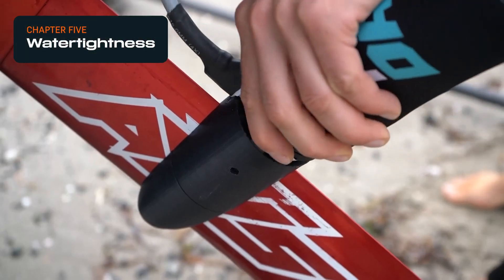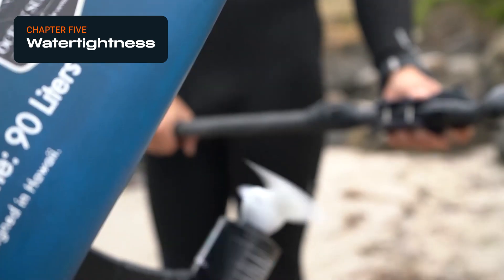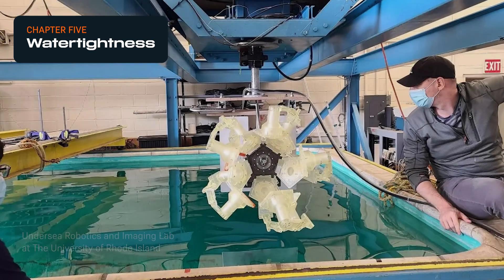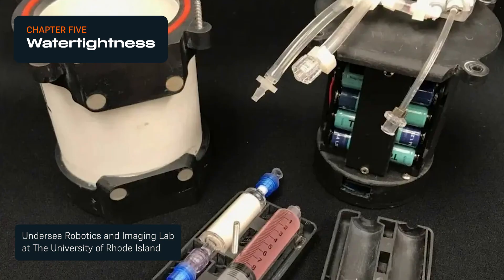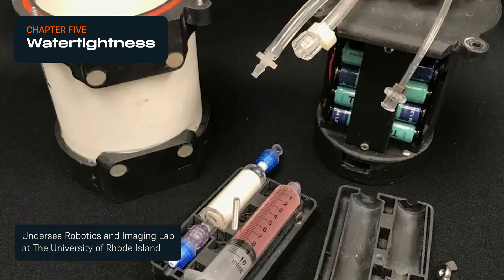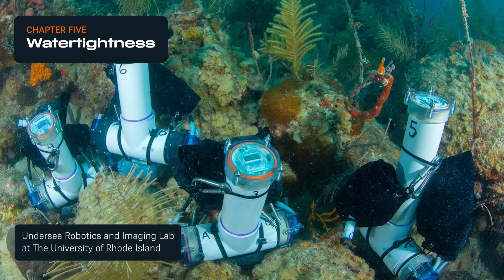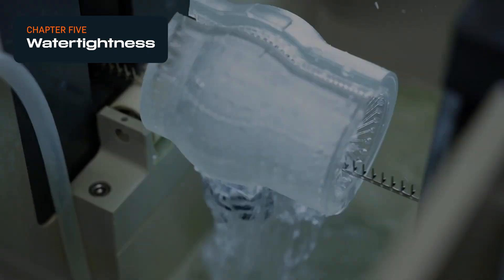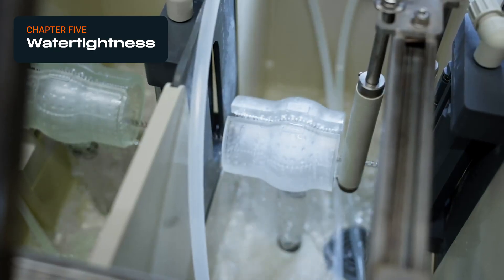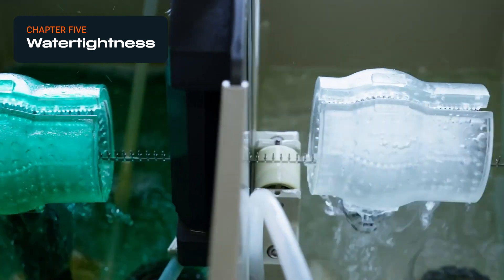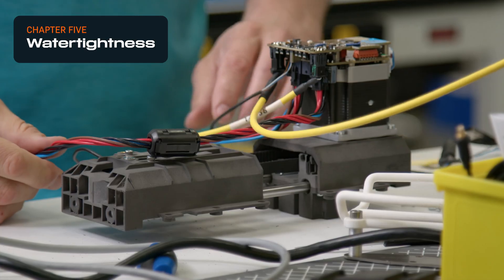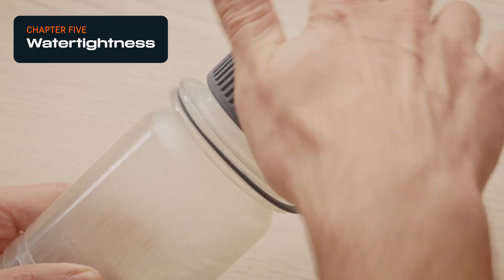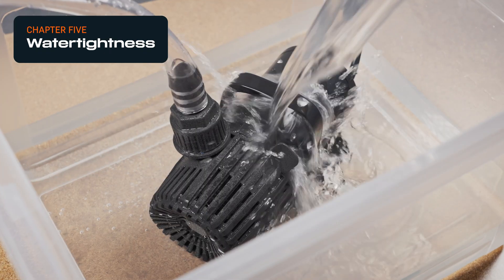Water tightness of parts refers to the ability of a part or assembly to prevent liquid from seeping in or out. In an extensive study done by the University of Rhode Island Underwater Robotics and Imaging Laboratory, FDM 3D printed robotics enclosures failed to keep internal mechanics dry under water for even a few seconds. SLA 3D printed parts were deemed water tight up to very high pressurization levels, and SLS 3D printed parts kept inner electronics dry under moderate pressurization levels, while vapor smooth SLS parts were able to stay water tight under increased pressure.